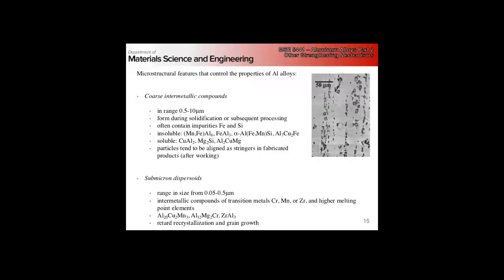Next, smaller submicron dispersoids of intermetallics. We're going to lump these in the range from 50 nanometers to 0.5 micron. These are the particles that are going to help us a lot with grain size. These are going to tend to retard recrystallization and grain growth.